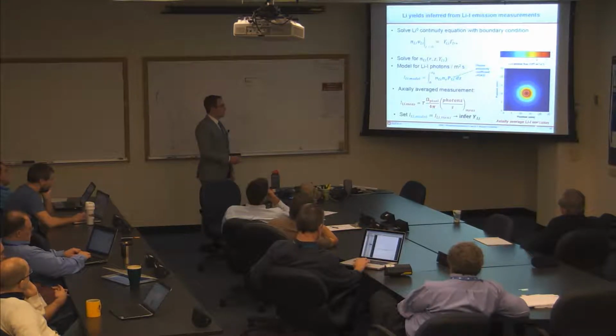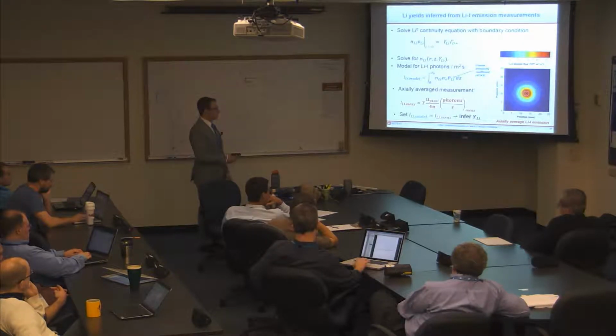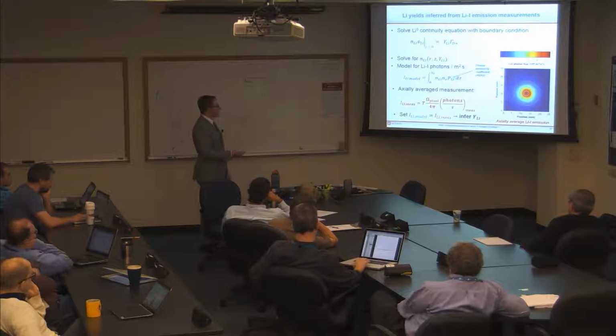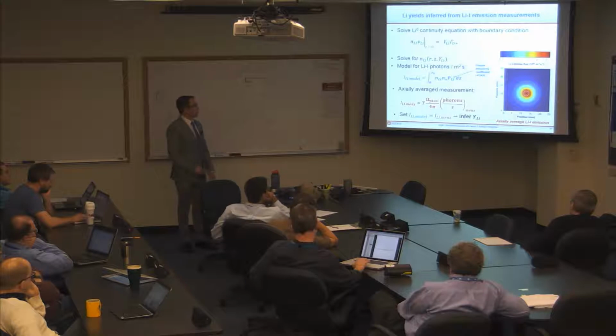And I've given some example measurements over here. As you can see, they're very radially symmetric, and so generally we radially average. That's expected because, like I showed you before, the plasma profiles are symmetric. It's an axis of symmetry in the plasma. So you set the measurements equal to the model, and then you solve for Y, which is the only free parameter left in the equation.